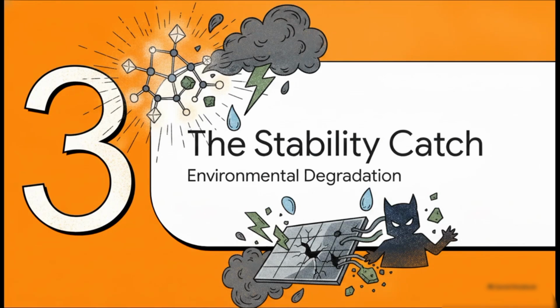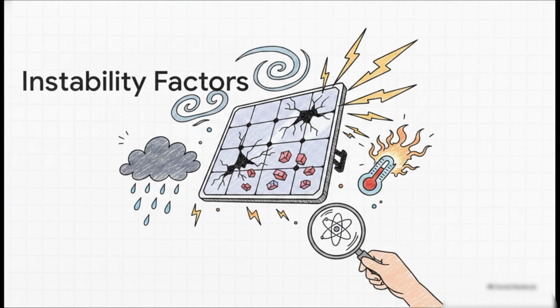Which brings us to Section 3, the stability catch, environmental degradation. So the villain of our story here is environmental degradation. Perovskite materials, as mind-blowing as they are in a pristine, climate-controlled lab, are incredibly delicate out in the real world. These cells are vulnerable to almost everything outside. They degrade super fast when exposed to moisture, oxygen, heat, and ironically enough, even the very light they're meant to absorb. They suffer from crystal defects and ion migration, which causes them to just lose performance over time.